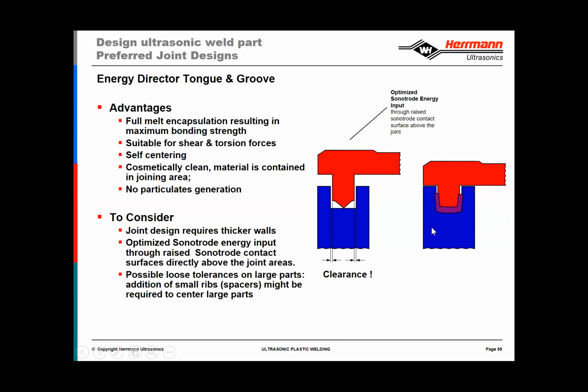The disadvantage, of course, is that the wall thickness of this part ends up being wider than you may be able to tolerate. But whenever possible, if you can fit the tongue and groove energy director into your design, this is really the go-to. And as I mentioned, having some clearance between the parts. They should not press fit together, but they should be loose, allowing the red part to vibrate in phase with the sonotrode, and allowing the blue part to remain motionless in the fixture. It gives the melt a place to go and fill into, but again, allows this part to vibrate freely together with the sonotrode.